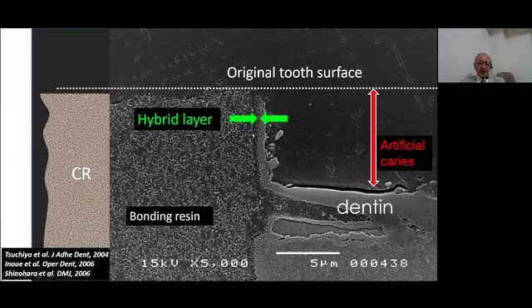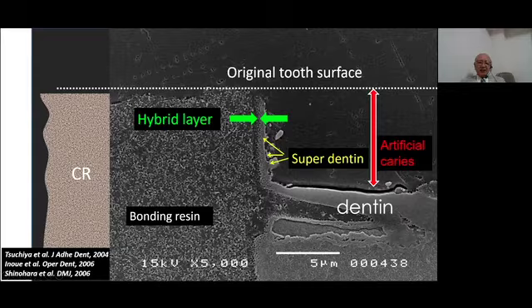And you can see the margin here, a very thin hybrid layer is observed, and adjacent to the hybrid layer, we still observe the dentin-like structure here. This dentin-like structure was resistant against the acid and basic attack. So that's why we named this layer a superdentin. Superdentin was created with the excellent adhesive resin material applications. That's why in this kind of situation, the recurrent caries must be very well prevented compared to the other poor bonding interface.